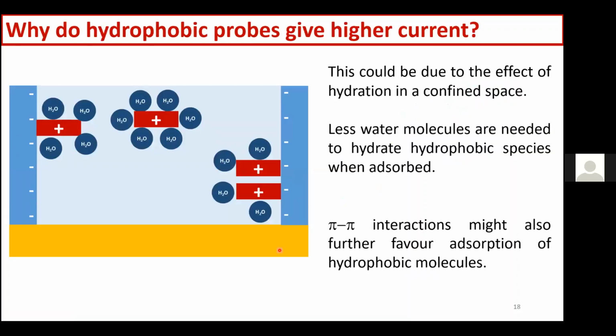So one of the reasons why we are adsorbing more paraquat, diquat, or methylene blue compared to ruthenium hexamine, for instance, could be due to the hydrophobicity or the organic nature of the paraquat. We need to remember that we are in a confined space of about 2 to 3 nanometers in diameter and approximately 100 nanometers in height.